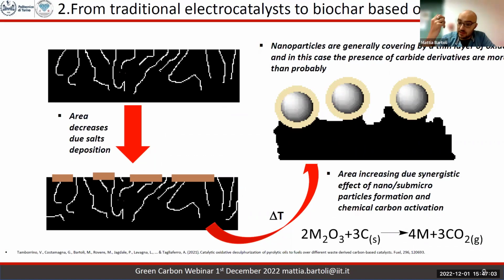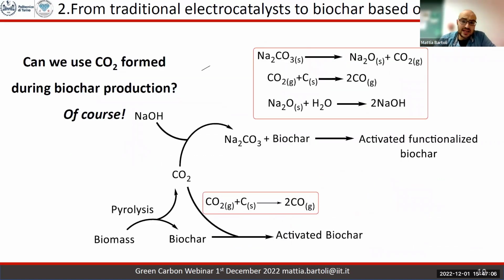So the other thing that we did is just insert oxygen inside the biochar by a simple activation process in different ways, or by recycling carbon dioxide that is formed during the pyrolytic process at higher temperature with a simple activation process, or by simply mixing with an inorganic salt, promoting the insertion of different functionalities. So we tried both physical and chemical activation, and the char that is produced displays a lot of oxygen functionalities, ranging from hydroxylic to carboxylic ones, and this will be helpful for different kinds of electrocatalytic activity that you will see in the next few slides.